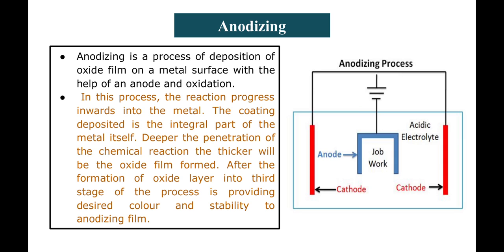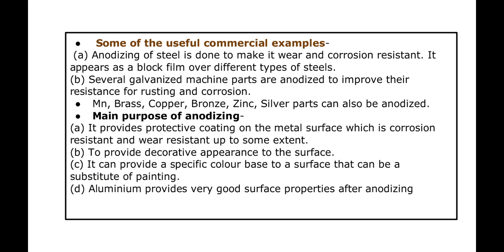An oxalic acid bath can provide an oxide film of a light yellow color, and the thickness of the coating depends upon the concentration of the bath, the density of the current passing through the electrolyte, and its temperature. The porous deposition can also be sealed by applying oil or wax to it. Anodizing of different types of metal is possible, and some useful commercial examples I have discussed here.